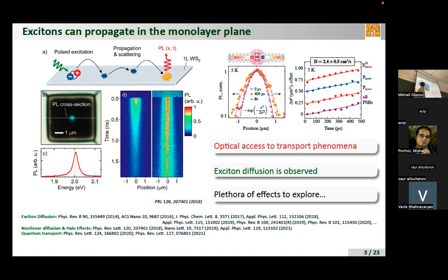This is a coordinate result within a several micron range, and a time result, the spectrum of these excitons. If you look at the experimental data like this, nothing happens. It looks like the excitons simply decay. But if you normalize this distribution by the maximum intensity, so you disregard the fact that excitons have a finite lifetime and die at some point, then you can clearly see that the distribution becomes wider in the course of time.